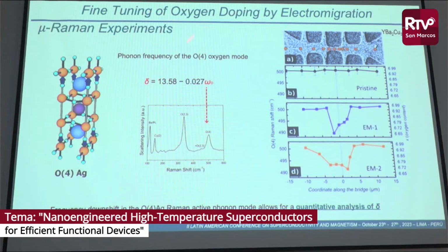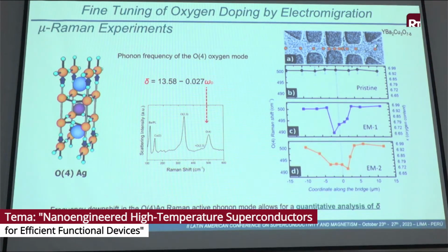And by doing so, what we have done is try to explore, after different electromigration runs, what would be the oxygen in our system in different positions of the track. And what we see is that in the pristine state, we have the proper oxygen content in the system, the delta that corresponds to a well-oxygenated state. And when we go to different electromigration runs, we observe that in the central part of the system, where we have the large amount of electric field, we have a concentration of oxygen vacancies.